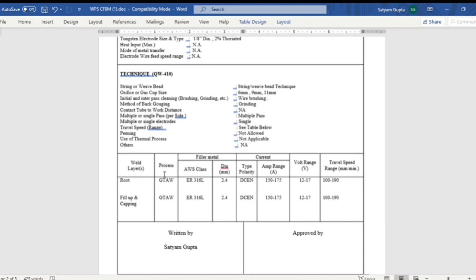And very essential, you can see the table mentioned below where the welder needs to refer to root welding, GTAW process, ER316L electrode, dia 2.4, polarity type DCEN, and what ampere he needs to use, like 150 to 175. The current range shall not be beyond this range. It must be in this range. This is very essential and we need to take care. If a welder is doing anything higher, it is not acceptable. Voltage range is defined there. Voltage must be in this range. Travel speed is defined there. The welder needs to follow this travel speed.